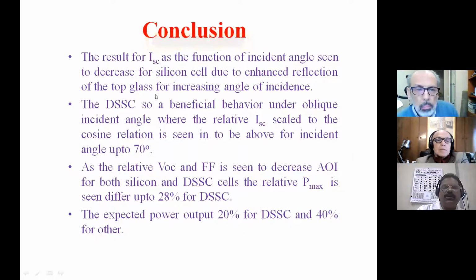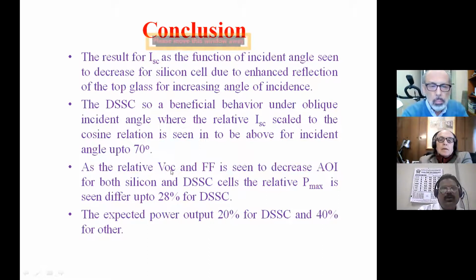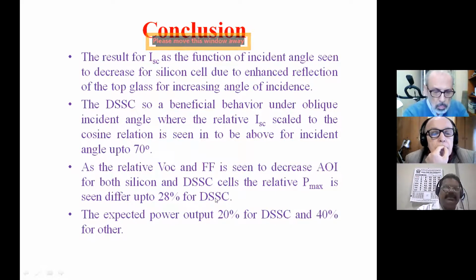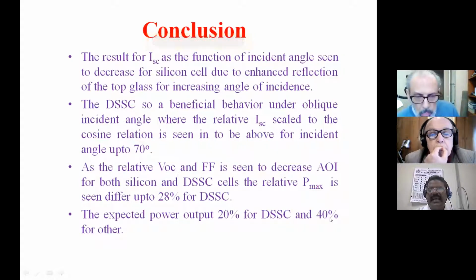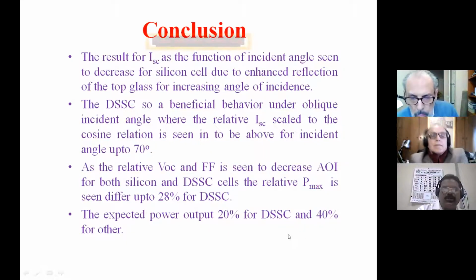This also concludes that the relative open circuit voltage and the fill factor are seen to decrease with the angle of incidence for both silicon and the dye-sensitive solar cell. The relative maximum power is seen to differ up to 28% for DSSC. So the expected power output is 20% for DSSC and 40% for silicon solar cells.